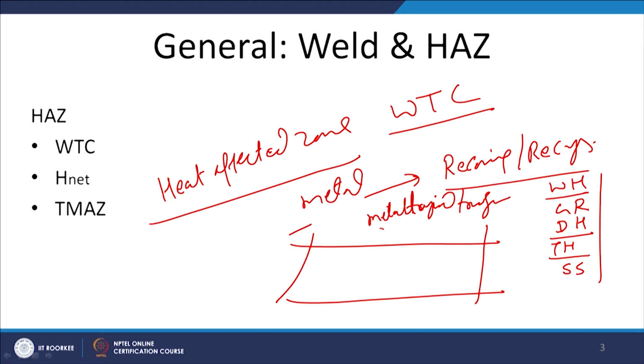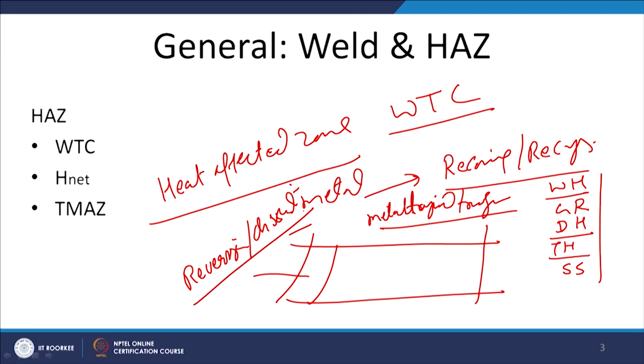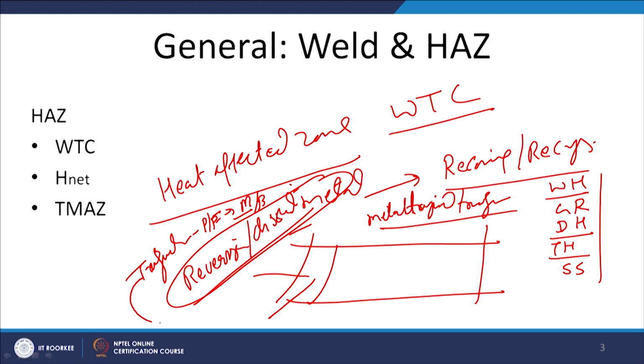in the heat affected zone, in the form of reversion or dissolution of the precipitates, or the transformation of ferrite and pearlite into martensite or bainite. So the reversion and dissolution will cause softening, while the transformation hardening will cause the hardening of the heat affected zone. Sometimes, that will depend upon the kind of strengthening mechanism which is involved.